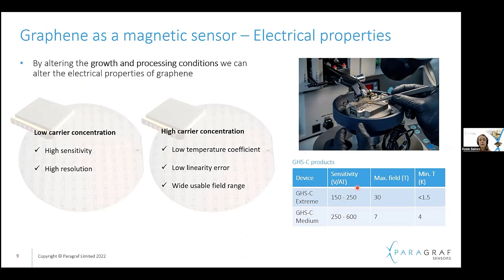The reason for this is that we might want to maximize certain properties that allow us to operate under certain ranges of conditions. For example, a low carrier concentration results in a high sensitivity and high resolution. This kind of setup would have advantages, as it wouldn't require lots of extra amplification of the signal. Alternatively, we can go to higher carrier concentrations, and this results in a lower temperature coefficient, lower linearity error, and a wide usable field range at these low temperatures. That's something we can take all the way through into our end devices and end up with tailor-made devices for these various conditions.